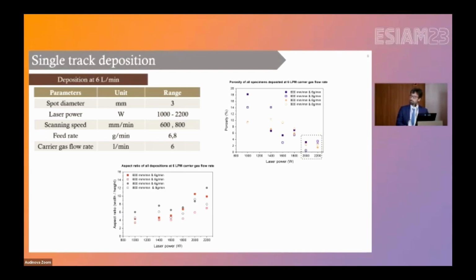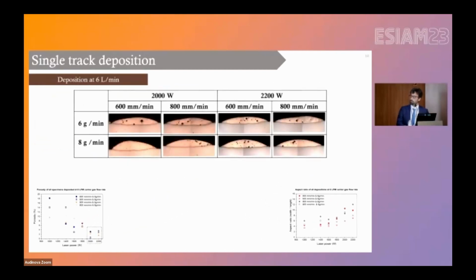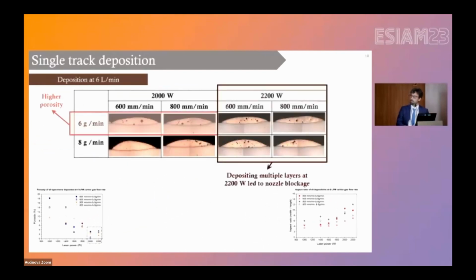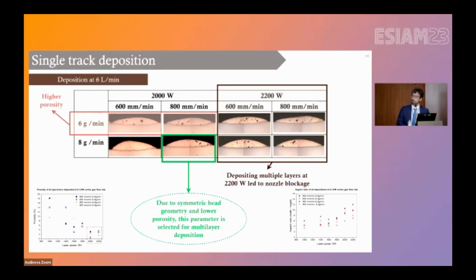Okay, so here you see the results in which we interpret the quality of the tracks in terms of aspect ratio and porosity. And so we selected the process windows here, shown in green, that guarantee the best shape, the best aspect ratio, and the lowest porosity in addition to dilution.